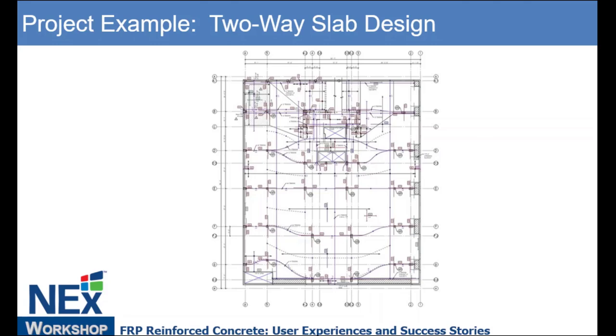So if you have a parking slab, and it's very common in big concrete slabs, find a large concrete slab that doesn't have at least one crack. Pretty hard to find, right? So with parking structures, despite our best intent during design and great construction, you put them through a few thermal cycles, winter to summer, you load them up, use them for a couple of years, you're going to have a few cracks. And when they crack, the calcium nitrite is essentially useless, because now you're going to have chloride saturating that steel.